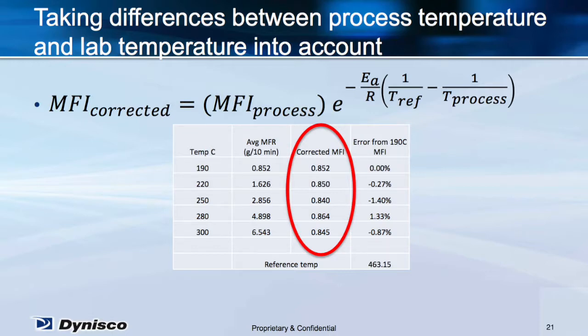First, I would say that the melt index testing was done by an operator in training. Second, I would say that the actual material is 100% recycled. We don't know its history. And thirdly, I would say that the result is pretty good over a pretty wide range in temperature. Of course, this correction needs to be evaluated for your specific process and material, but I can say that we've had pretty good luck with this correlation.